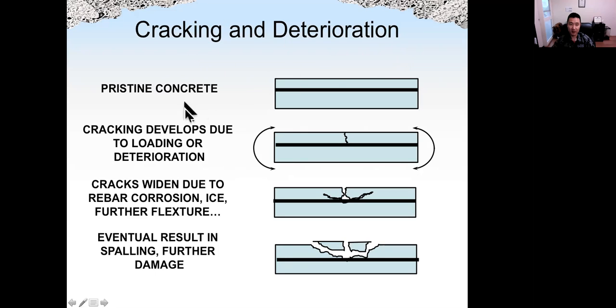So cracking and deterioration. When we have pristine concrete, there's no cracking, as long as the concrete is cast accordingly. Then cracks will occur due to loading or deterioration, such as shrinkage. When concrete has a crack, the crack will open up because water will bring harmful materials inside the concrete and do further damage. And the loading will, again, open up the crack. So the crack will initiate deterioration, and the further deterioration will facilitate further cracking. So eventually, concrete will fail. The rebar protection, the concrete cover, will fall off.